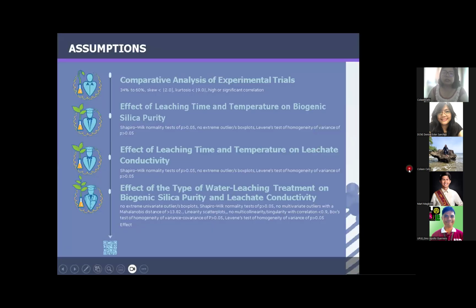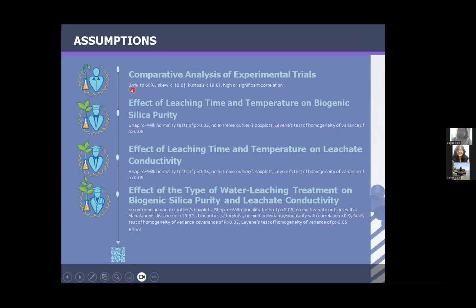So this is for the results and discussion. I'm going to talk about this because it is related to my statistical analysis. I need these assumptions, except for this one, because it depends on the method I used, which is gravimetric. The values of my purity should fall between 34 to 60%. I was distraught because the first title of my pipeline defense was high purity biogenic silica, which is 90% and above, and that is not what I produced. The reason is that this assumption is that the method can only detect between 34 to 60%. So if the majority of my data falls within this, it is acceptable.